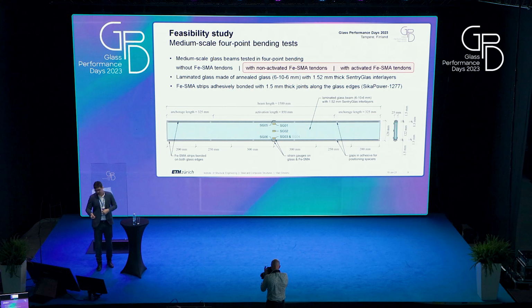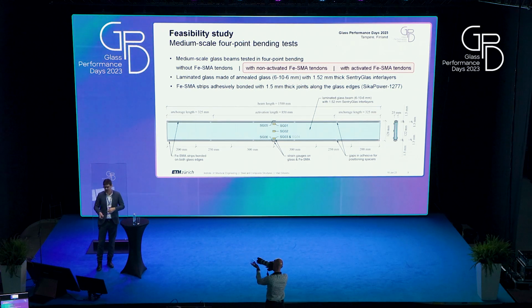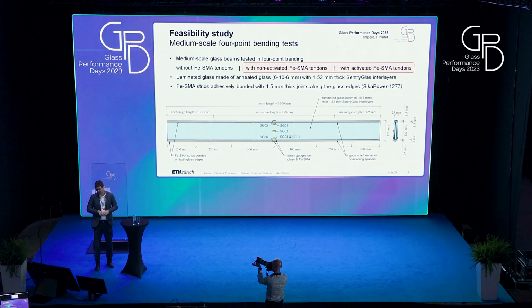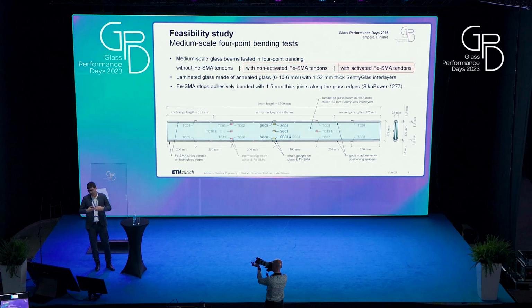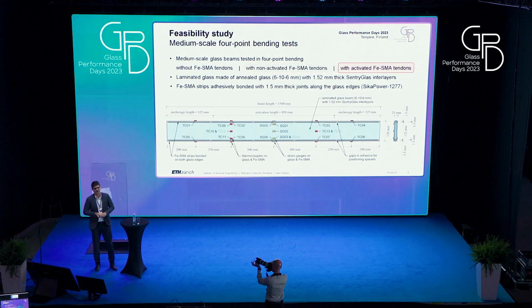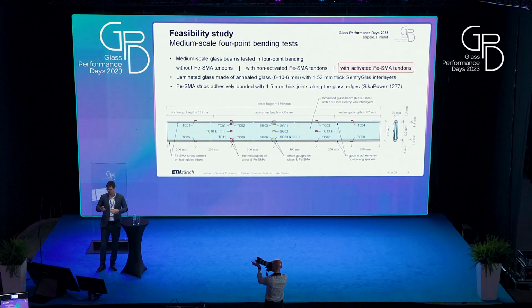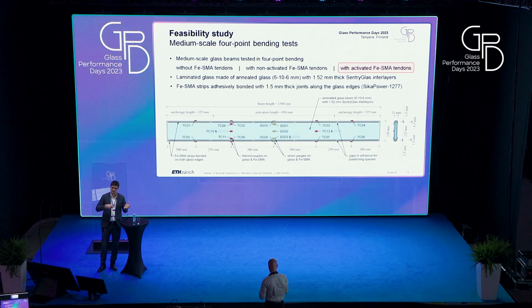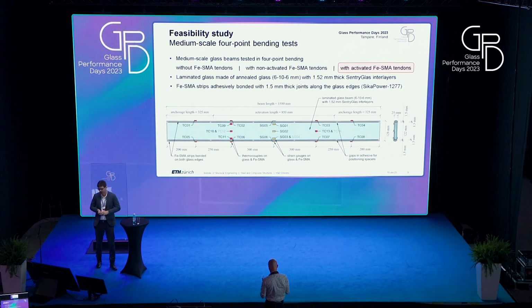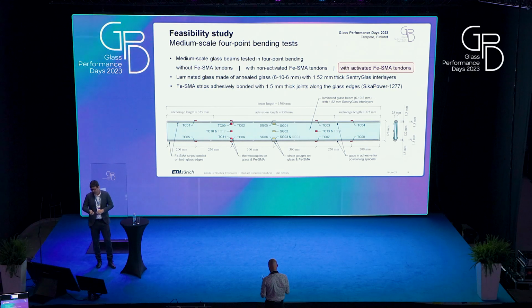For the pre-straining, for the activation, as well as for the test, we had strain gauges to monitor the strains in the middle of the glass at different positions. And for the activation, we also used a high number of thermocouples to monitor the temperature on the glass surface, as well as on the shape memory alloy strips.